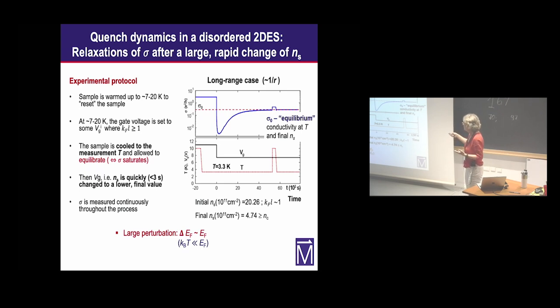At time equals 0, because we are reducing the carrier density due to the field effect, the conductivity drops immediately, but it does not stop at this red dashed line. Instead, it overshoots it, in this case by more than an order of magnitude, and then it starts slowly approaching this line. Note the time scales of the order of 10^4 seconds, 10,000 seconds and more. So these are long, time-consuming experiments.